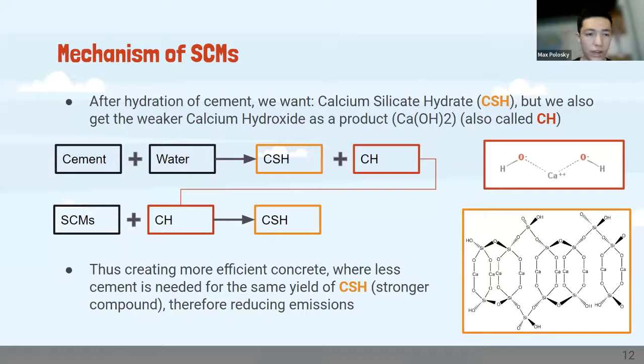But when we add SCMs, they can react with the CH, the weaker CH, to then create more of the stronger CSH that we want. And thus, we create more efficient concrete where we need less cement for the same amount of CSH. And therefore, less cement means less emissions.